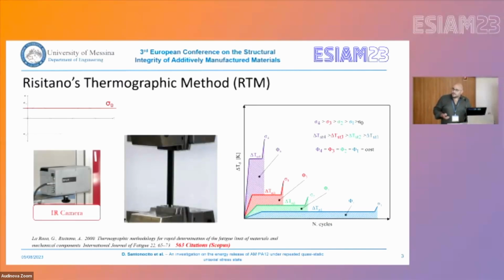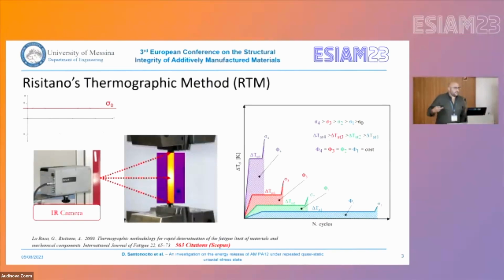If we stress a material in a cyclic way and we observe the temperature trend, we can see the first phase where an initial temperature increment is present, then the second phase where the temperature stabilizes, until in the third phase the temperature increases up to the failure of the specimen. The higher the applied stress, the higher the stabilization temperature. However, the subtended area of the temperature versus number of cycles curve, the phi parameter, so the energy parameter that can be related to the fatigue life of the material, is almost constant. So the basic idea is that I can divide the energy parameter by the different stabilization temperatures and obtain the number of cycles at which the material will fail if stressed with that stress level.